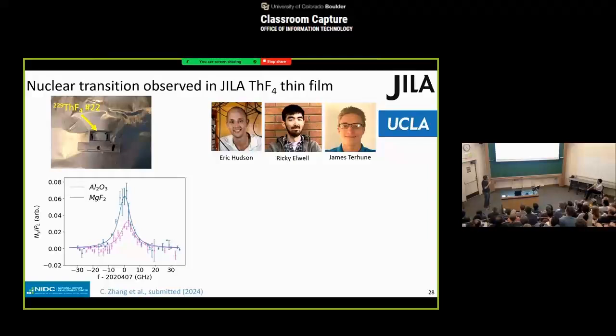And there's another sample that we sent over on a different substrate. So you can see these two different lines represent the spectroscopy results from these two samples on different substrates. And indeed, they both show up exactly where you expect the thorium nuclear transition to be. And the spectroscopy line width here is also about 10 gigahertz, and that's still limited by the broadband laser system used at UCLA.